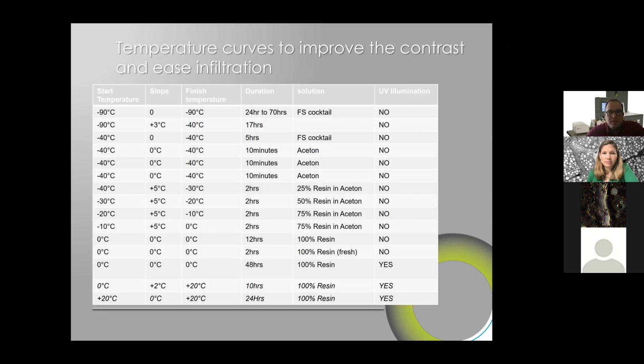Another point that was raised by Paolo Ronchi from the MBL during this ZEISS meeting was the slope at which the temperature should be raised during the freeze-sub cocktail. And he said that in their hands, now instead of raising the temperature from -70 to -40 at 5 degrees per hour, they're going 3 degrees per hour, and this increases the contrast significantly. So this is something I will try myself and see how much it influences the quality. But obviously, this remark is important, and I will integrate that in my forthcoming work.